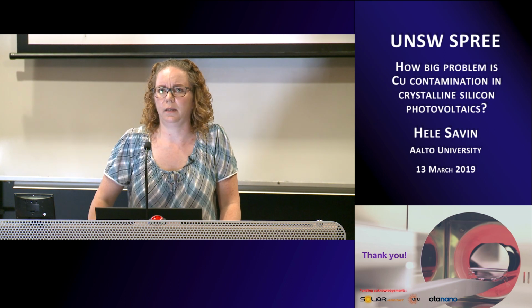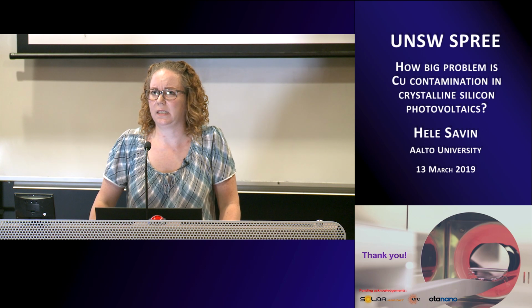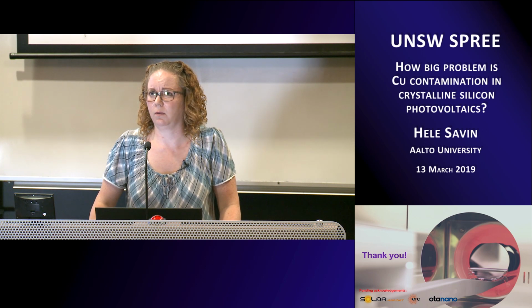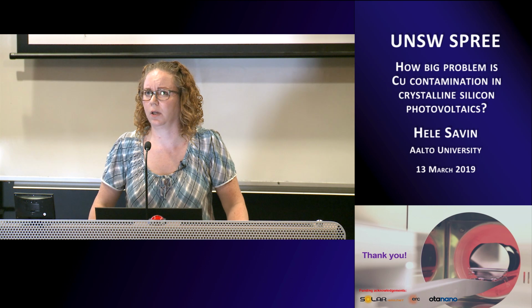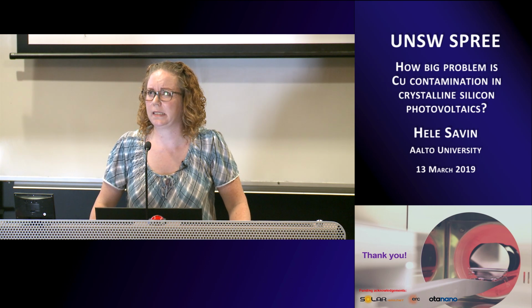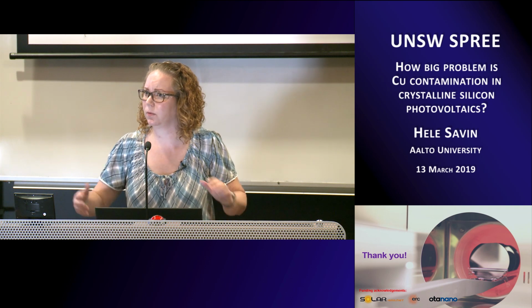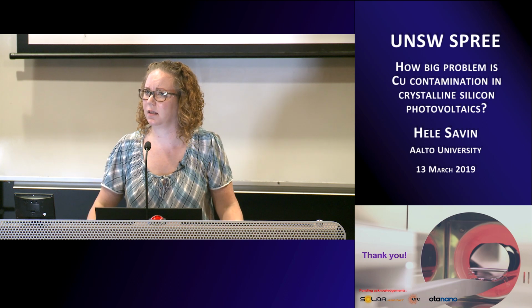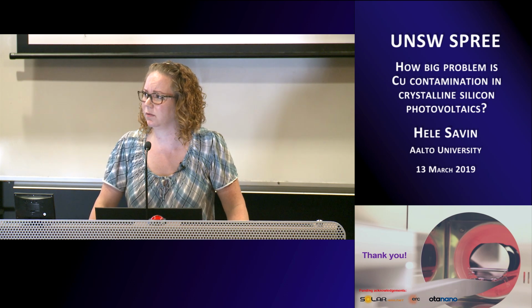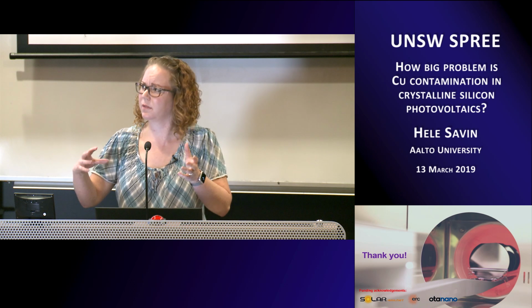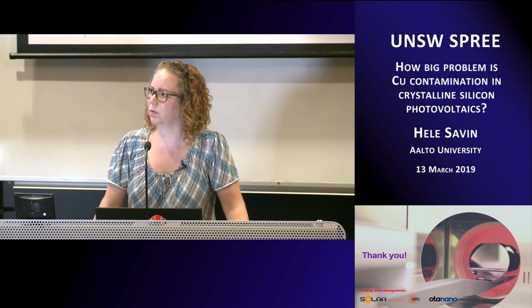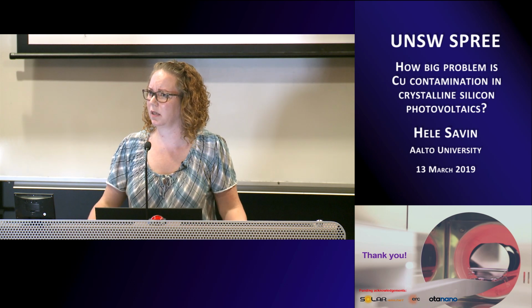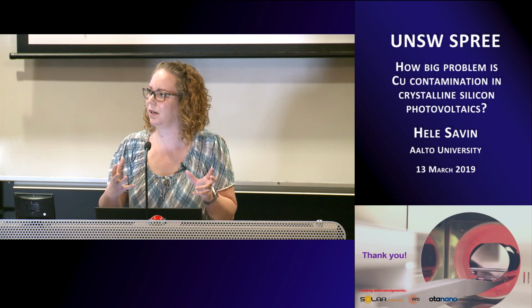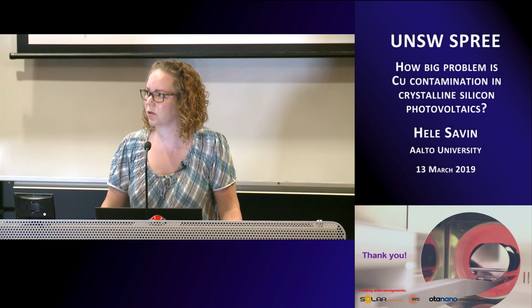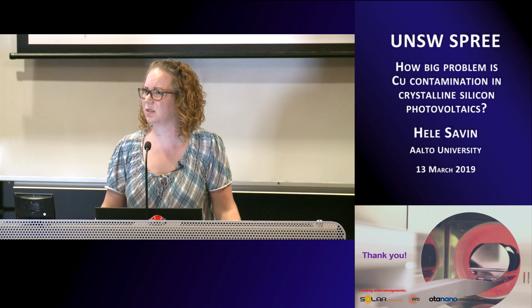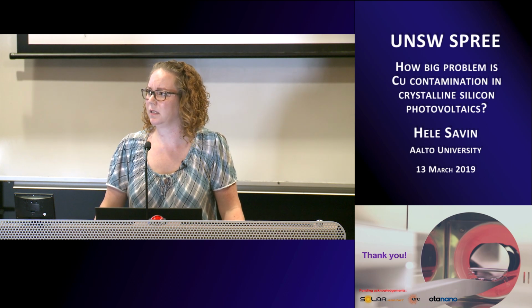Yeah, so I think copper solubility in P-type silicon is relatively well known. What we haven't found out is the copper solubility in the emitter. There's some data about iron solubility in phosphorus-doped silicon, and we used that as a first approximation. That's the data that is missing from the literature, because it's also very difficult to measure. But I think that should be the same order of magnitude.